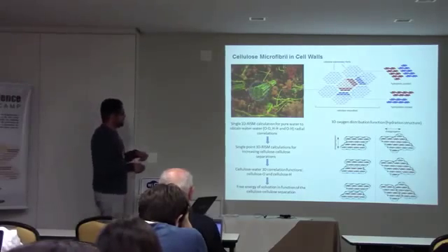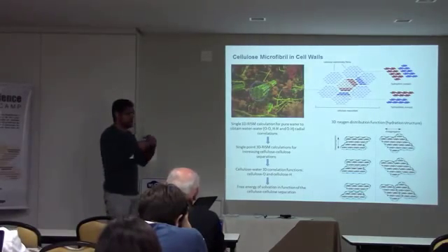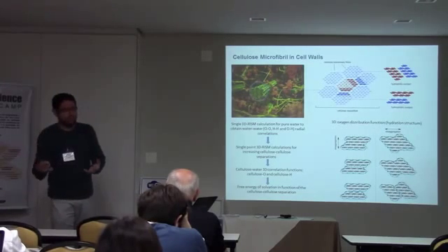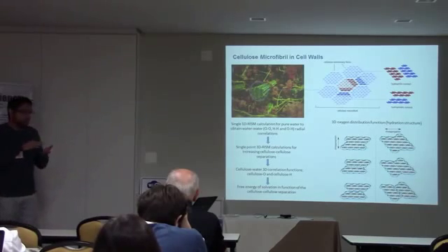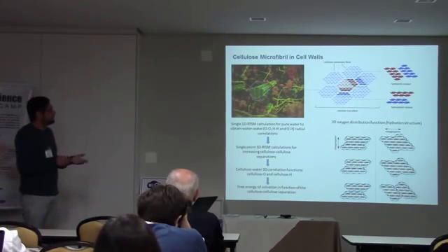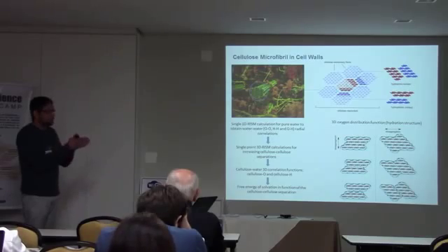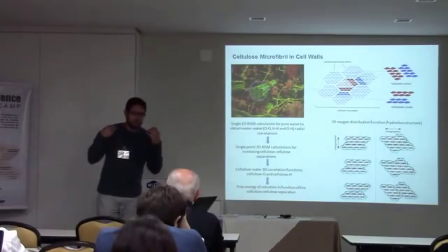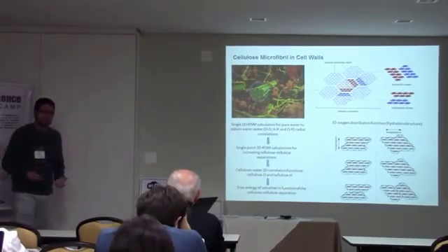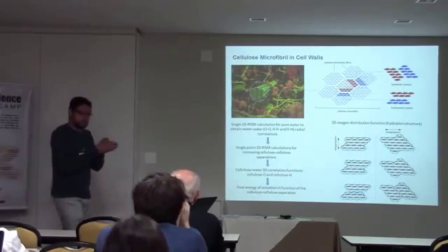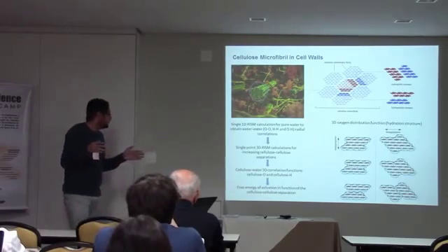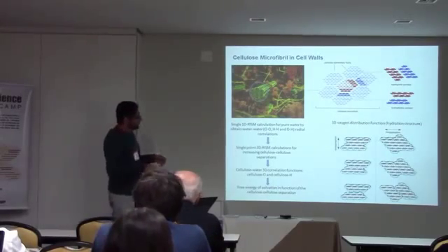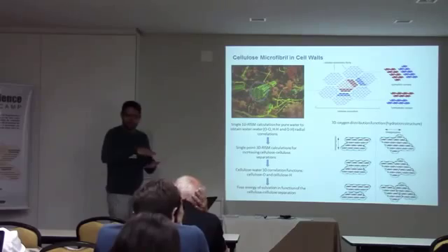So instead of just computing the density, the hydration structure around a given cellulose fiber, we can take just two cellulose fibers, for example, in this scheme, and move them apart and solve the three-dimensional equations for every separation and get the structure, and from that get the thermodynamics as a function of the distance of the cellulose. So here we have the solvation structure as a function of the separation.